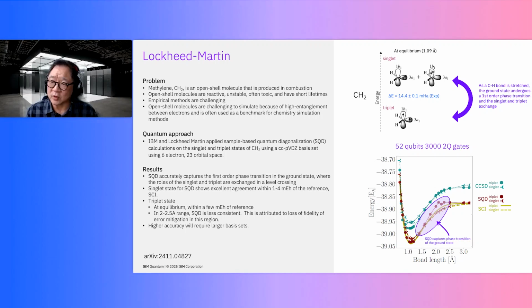The singlet is the lower energy state and the triplet is the higher energy state. This is at equilibrium. But as you stretch one of the carbon-hydrogen bonds, the molecule actually undergoes a phase change. The triplet and the singlet states switch energies, and beyond a certain bond distance the singlet becomes the ground state, and the triplet becomes the more excited state. And if you look at the results down in the bottom here, you can see the ground state energies as a function of the CH2 molecule, as a function of the one carbon-hydrogen bond length.